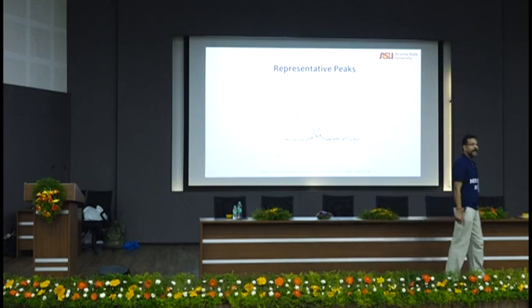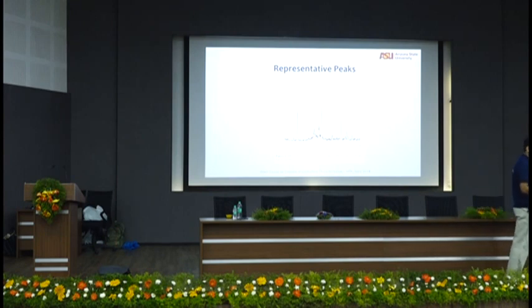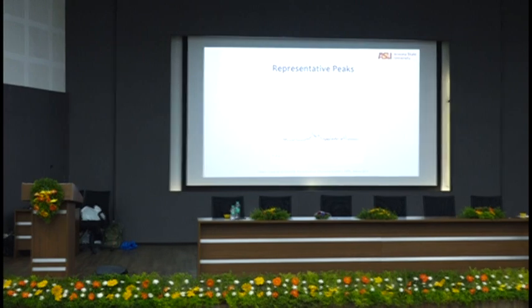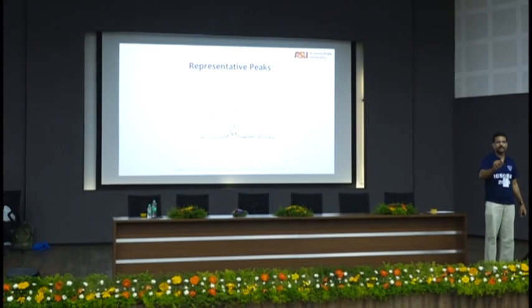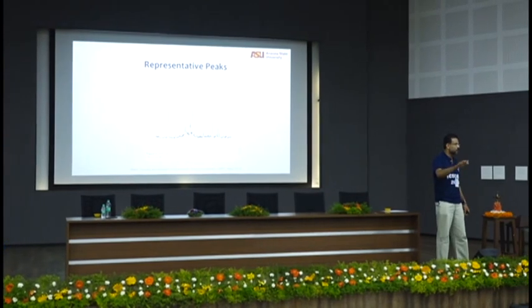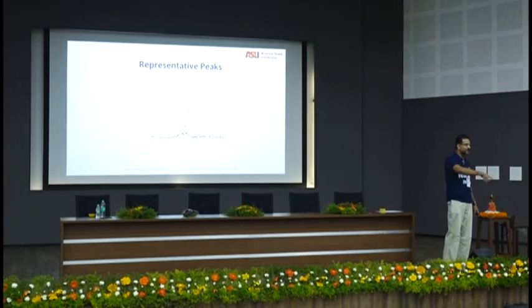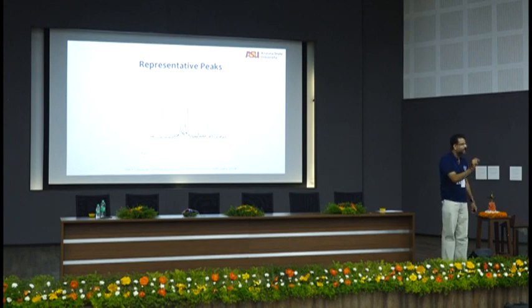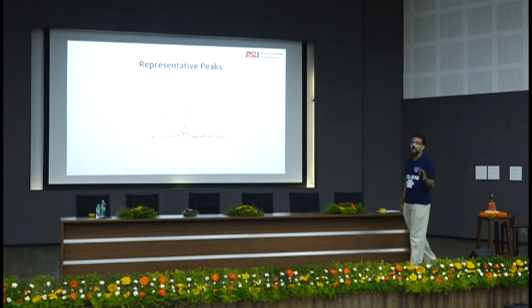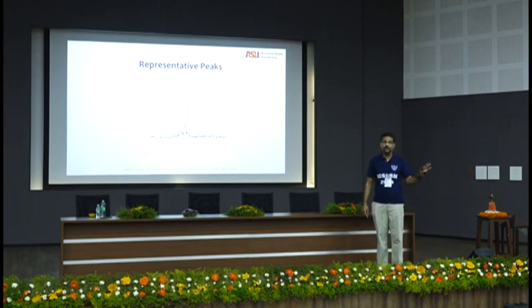If you are doing a mortar with quartz sand, you will get beautiful, so many peaks of quartz that you can guarantee. I would encourage you not to do X-ray diffraction of mortars if you have to understand what's in your cementitious system, because quartz masks a lot of other things. The quartz peaks are so large that even the other larger peaks seem very minuscule and you can't find them. So if you're interested in finding out, always do a paste, not a mortar.